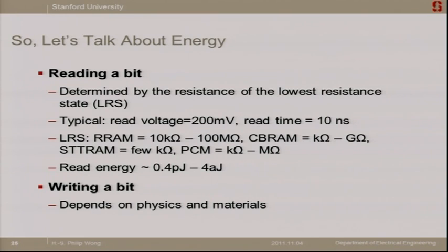The low resistance states for this metal oxide RRAM and the conductive bridge memory can span many orders of magnitude, because it's a filamentary conduction. For the CBRAM, you can grow this filament to be very thick and have very low resistance, or you can have one atom touching, and you have very high resistance in the low resistance state. Similar for the metal oxide, you can have many filaments forming, and therefore your resistance will be very low, or you could grow the filaments fatter, so it can be very low resistance. So it spans a very large range of resistance states.